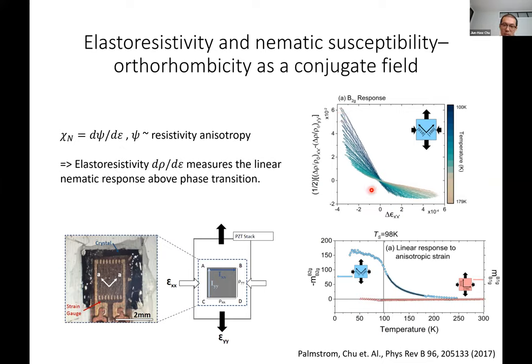But in the same measurement, we also show that the rho xx plus rho yy actually responds quadratically as a function of strain. And the quadratic coefficient is positive. So that means that when you're making a system more anisotropic, simultaneously, the isotropic average resistivity also increases.